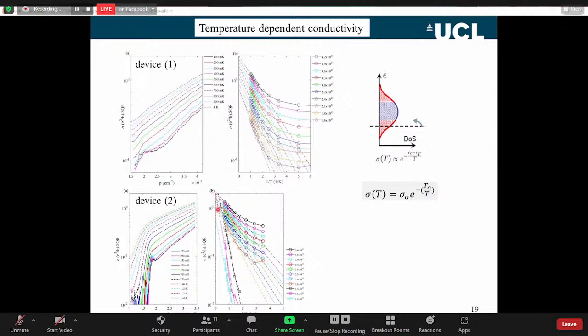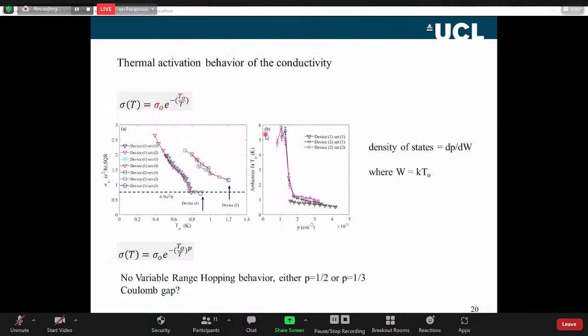We plot this data out as a function of 1 over T, log sigma versus 1 over T. We've got the straight line behaviour, and then we've got this sudden increase at around 1.5 or 6 times 10^11. We plot out the parameters from that fit. What I'm plotting here is, for each data set, at fixed carrier density, the Arrhenius behaviour for activation, and the 2 parameters that come out of the fit, those straight line fits, are sigma naught, that's the high temperature intercept, and T naught, that is a measure of the gap between the chemical potential and the mobility edge.